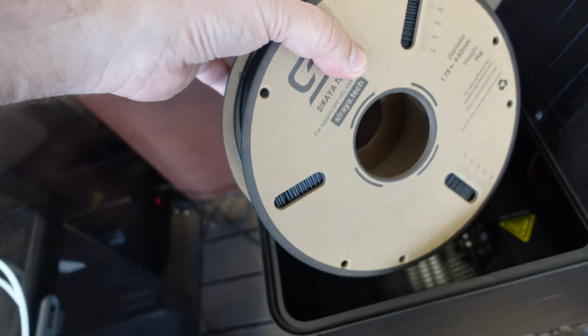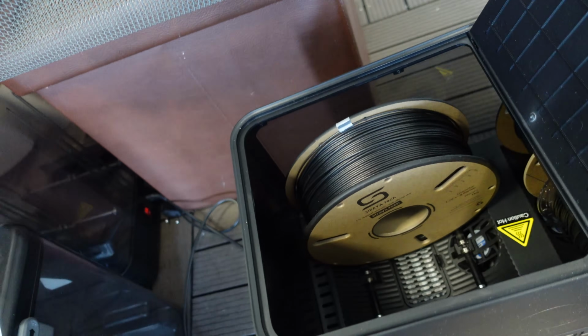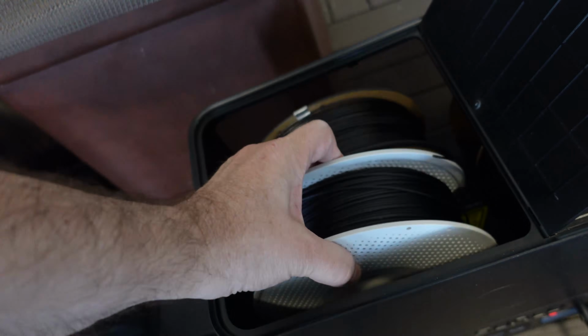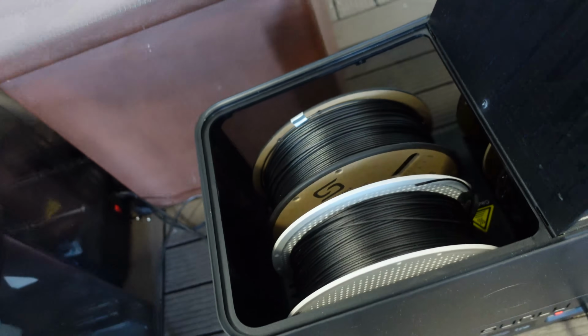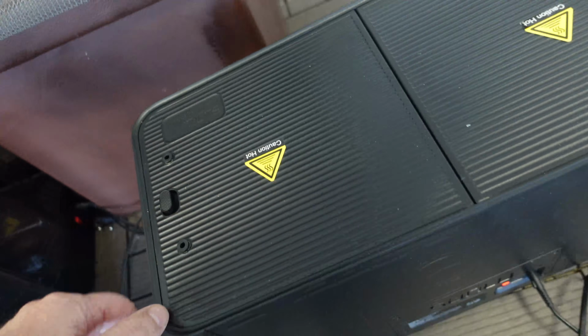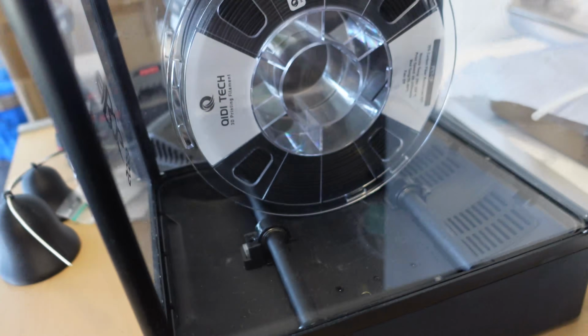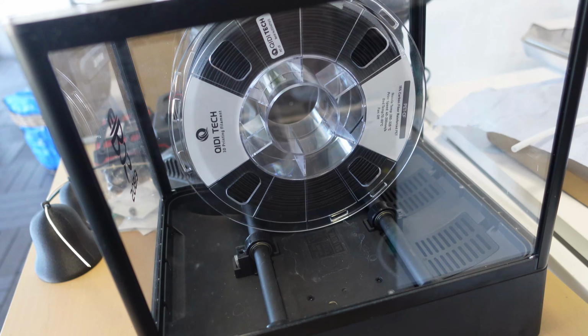They are sensitive to moisture, and one of the checking methods is to print some small box and measure it. If it is bigger, like over extrusion, probably the filament needs drying. It's bigger because of those micro water drops inside the nozzle. They boil and push out more material.